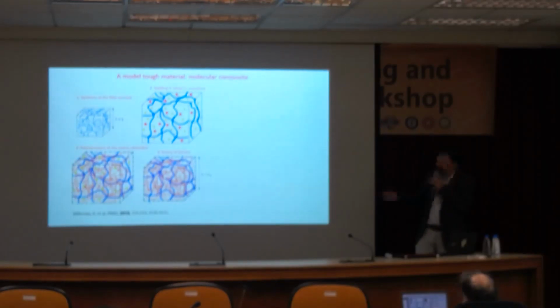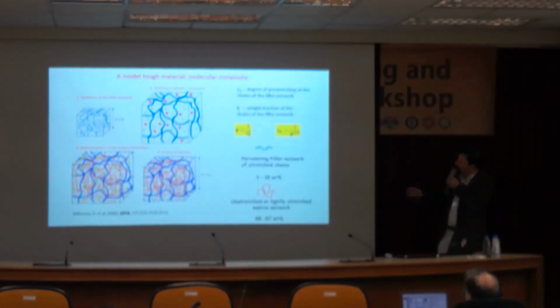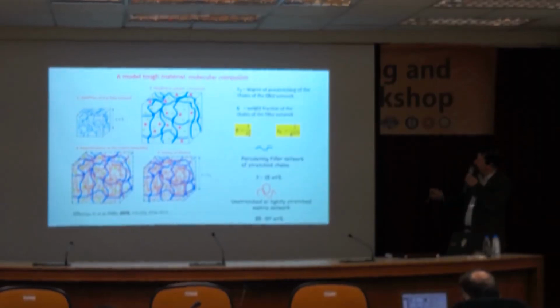In the next step, we do this by UV polymerization, but you could do it by other means. You can transform this monomer part into a polymer. So you're making a polymer inside this first network here. This blue one gets, in this way, stretched. In the last step, you evaporate the solvent, so you have a little bit of shrinkage, and your final piece of material here is larger than the initial one by the factor lambda 0 in all three directions. So you have isotropic stretching. The blue chains are being stretched because they cannot really move apart, while the red chains are just random chains, random coils in the statistical mechanics sense. Now, an important parameter in these kinds of materials where you can really change the design is the volume fraction of the blue chains in there and also the pre-stretch.